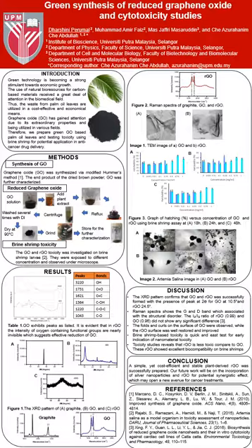The TEM image shows folds and curls on the surface of graphene oxide, while the reduced graphene oxide surface was well restored and improved. Brine shrimp-based toxicity is a quick and easy test for early indication of nanomaterial toxicity. Toxicity studies reveal that reduced graphene oxide is less toxic compared to graphene oxide. This reduced graphene oxide shows excellent biocompatibility on brine shrimp.